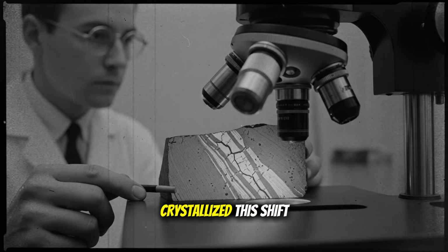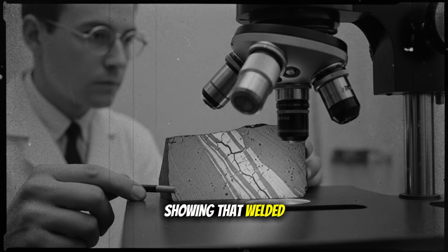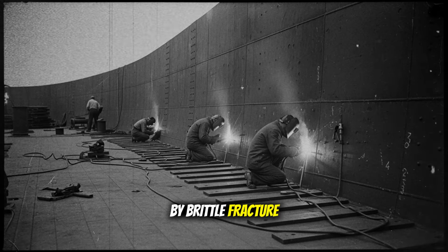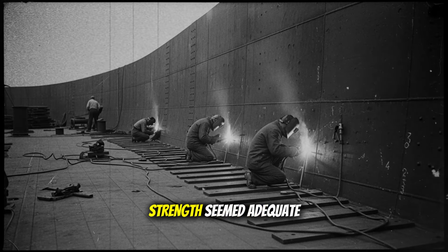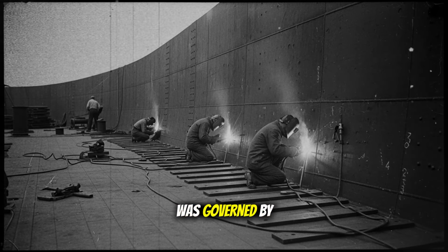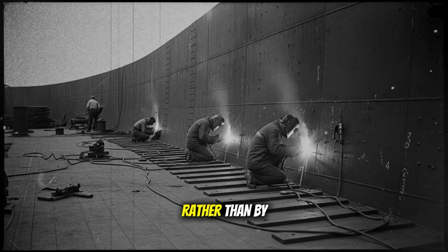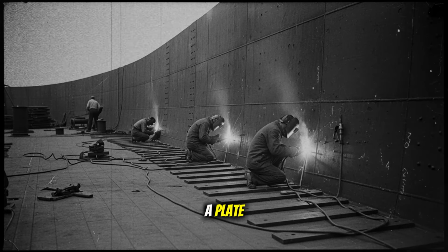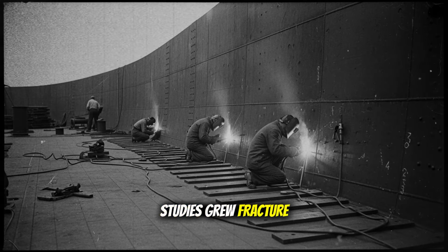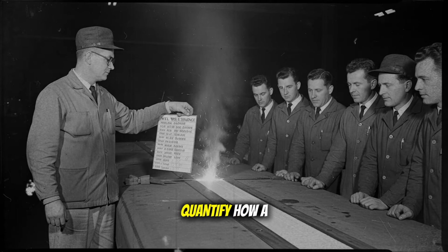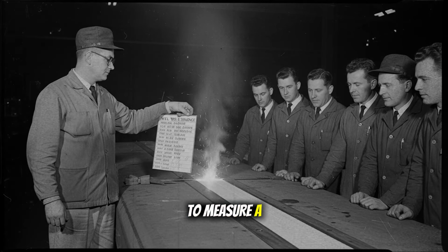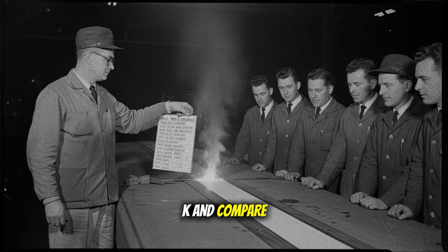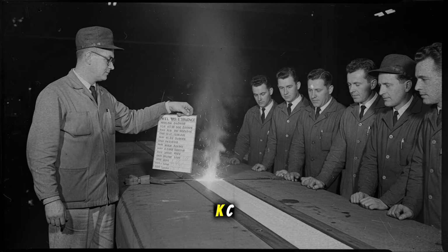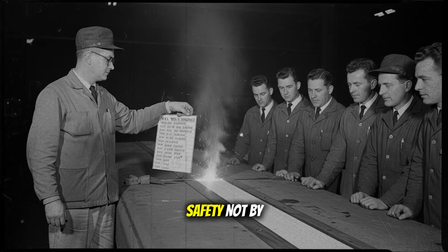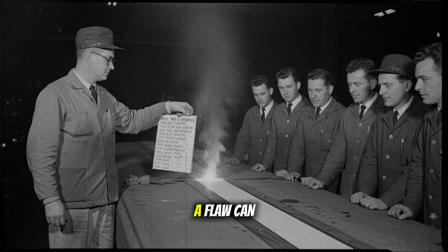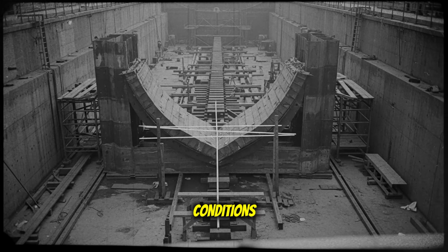Constance Tipper's work crystallized this shift, showing that welded ship steels could fail by brittle fracture at low temperature even when tensile strength seemed adequate, and that fracture was governed by how a crack tip concentrates stress rather than by average loads across a plate. Out of such studies grew fracture mechanics, a way to quantify how a crack behaves, to measure a stress intensity factor K and compare it to a material's fracture toughness Kc, and to judge safety not by a single strength number but by whether a flaw can grow under service conditions.